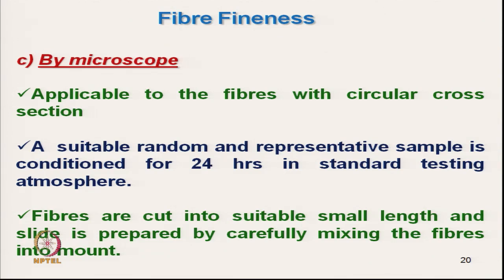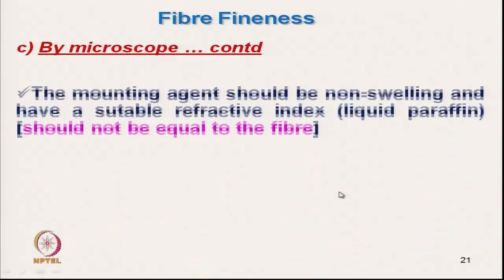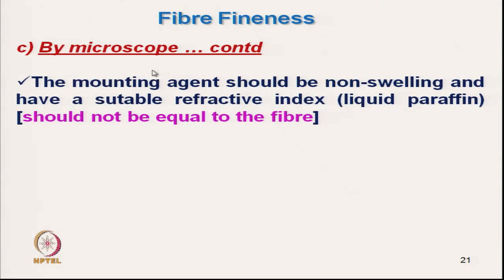with the mount, and then we have to mix it properly and carefully. The mount is selected in such a fashion that it should not swell the fiber, and the refractive index of the mounting agent should be different from the fiber.